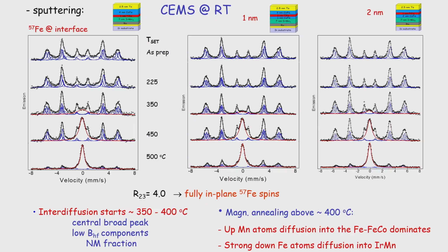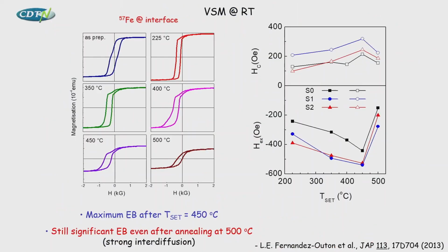And what we see by Mössbauer is that starting from, let's say, 350 degrees, we start to see interdiffusion in the samples, okay? And we start to kill the magnetic signal. And at 500 degrees, we have a strong interdiffusion, very few ferromagnetic phase remains. Okay. And if you look at the exchange bias, despite this big interdiffusion, we see that the exchange bias is maximum at 450 centigrade, which is really interesting. And you see that you have a maximum exchange bias, even if you have a very strong interdiffusion at the interface, which we were really not expecting, okay?